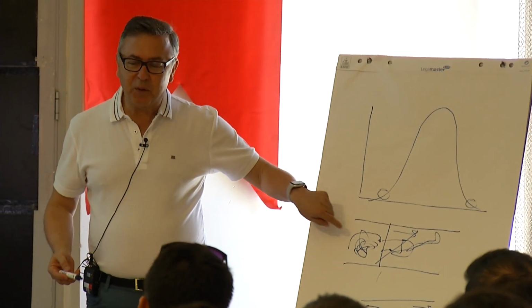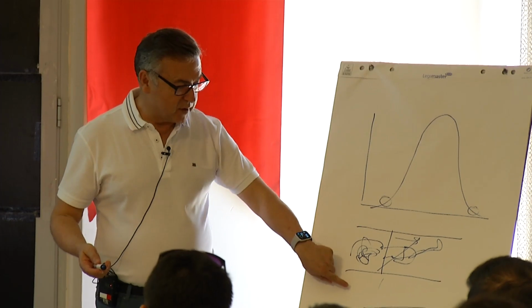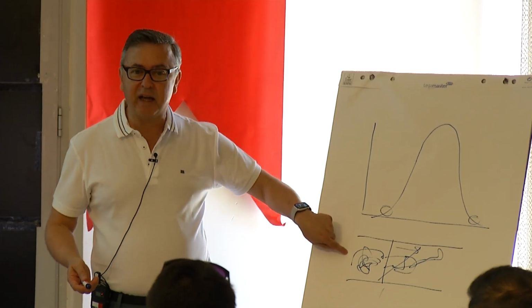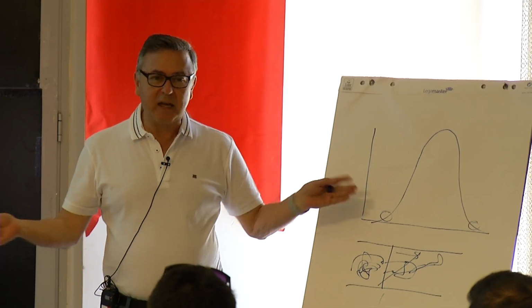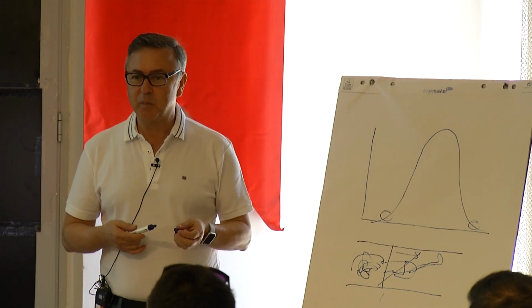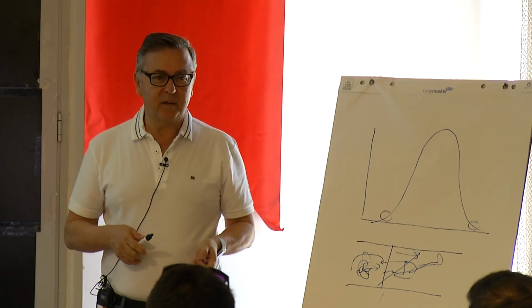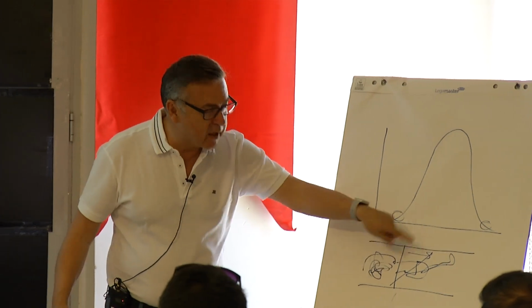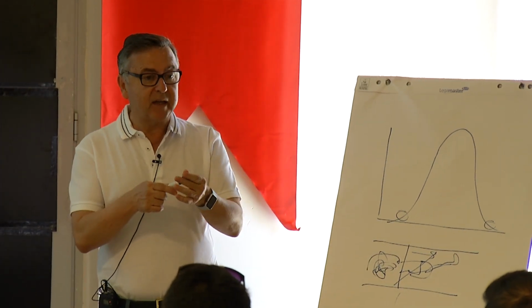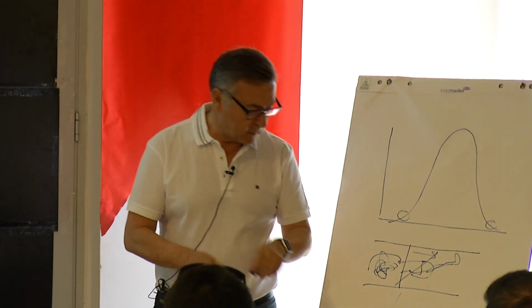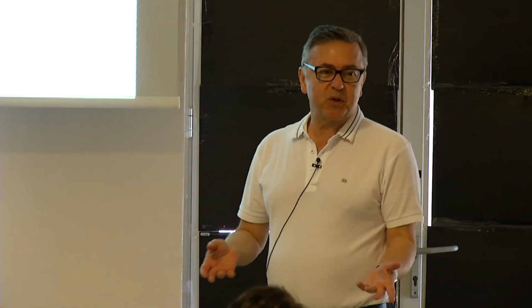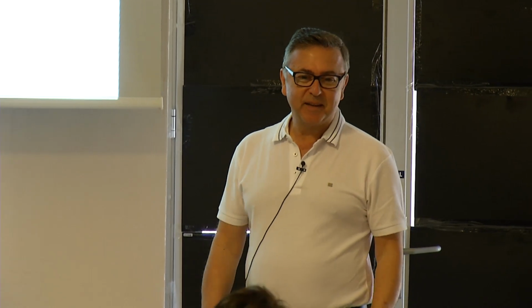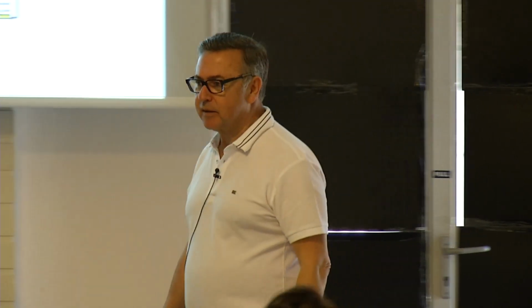So shear flow, yes, absolutely right. Elongation is much better because in shear you're wasting energy by rotating. Rotation, the so-called vorticity, has no effect on orientation. Only the elongation in the shear helps you stretch the polymer chains. So which process is the best? Fibers, right? That's why fibers get highly oriented.